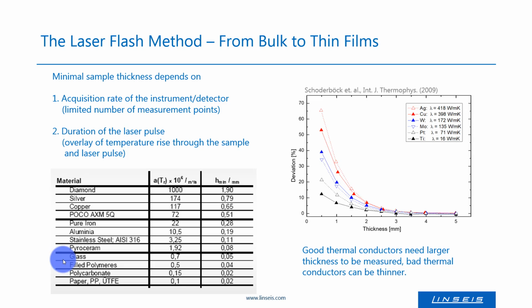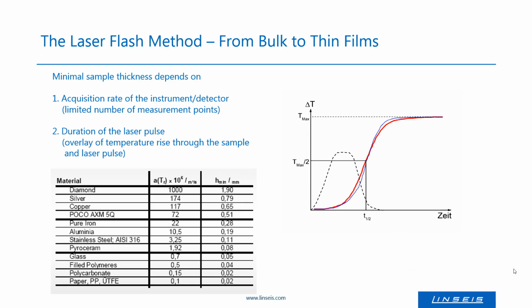Because of this, the classical laser flash technique runs into two main limitations. The first one is the problem of acquiring enough data points within the short time period of the experiment. The second one is the overlapping of the heating pulse on the backside with the temperature rise on the front side. Both effects lead to a measurement error depending on the sample thickness and thermal transport properties.